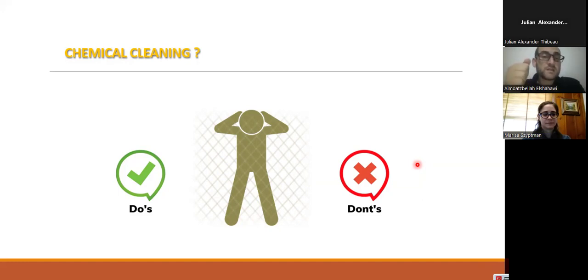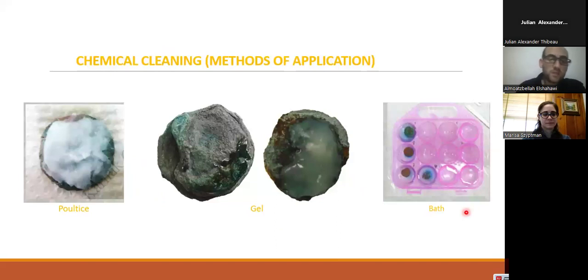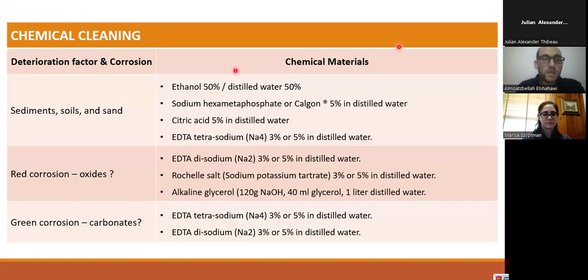First, you have to rinse the coins to return the pH to neutral using distilled water. And also you have to make a drying process to get rid of the water that you used in the washing process. Chemical cleaning methods, you can apply with a poultice, make a gel, or in a bath. Here's also an important table that you can use for these materials when you have these corrosion layers or